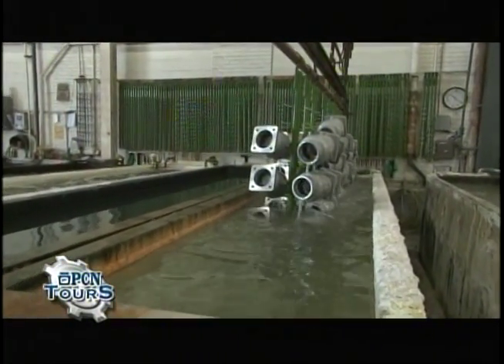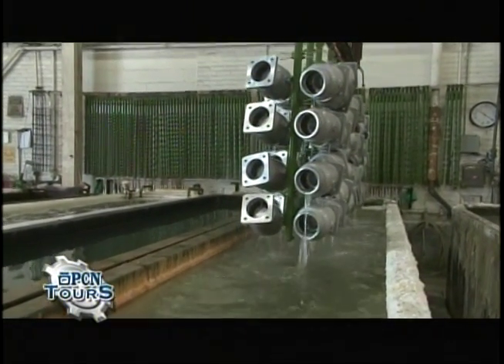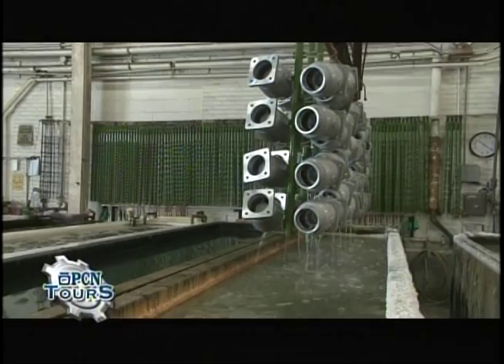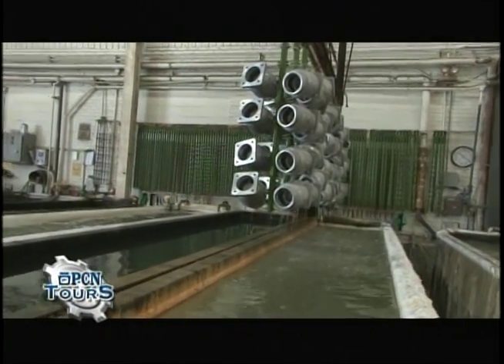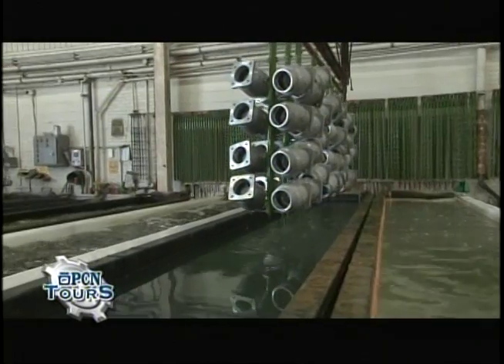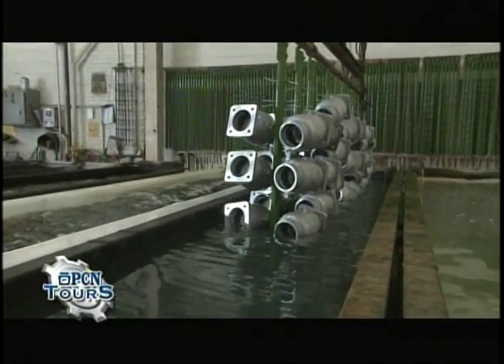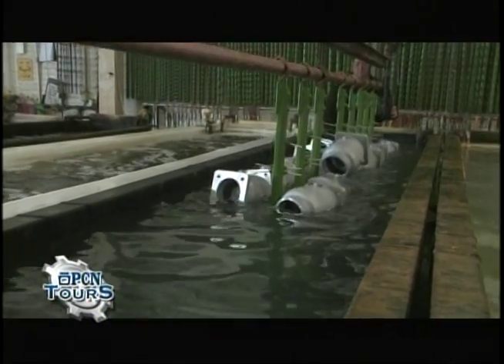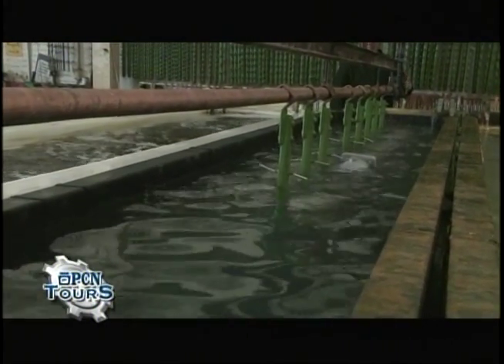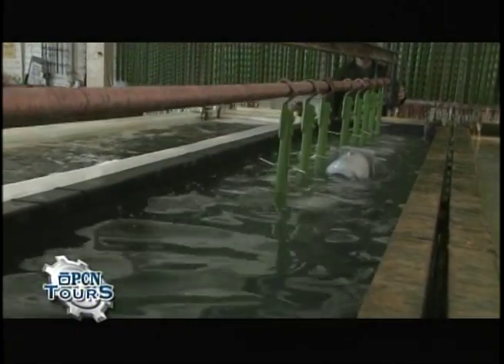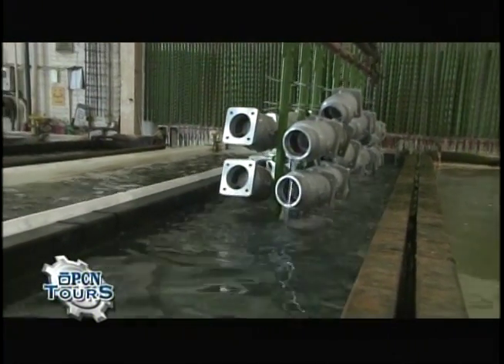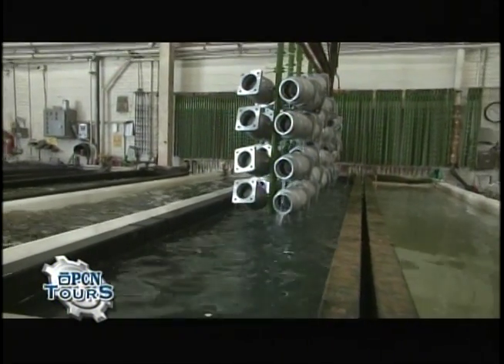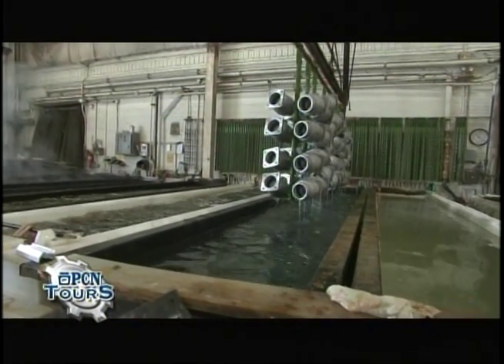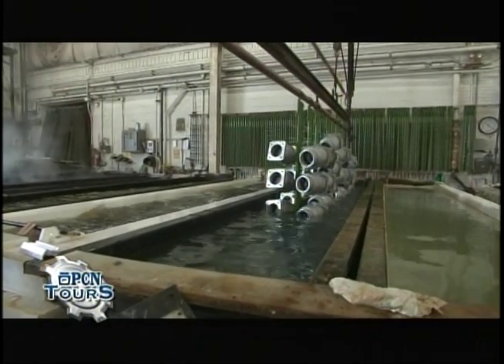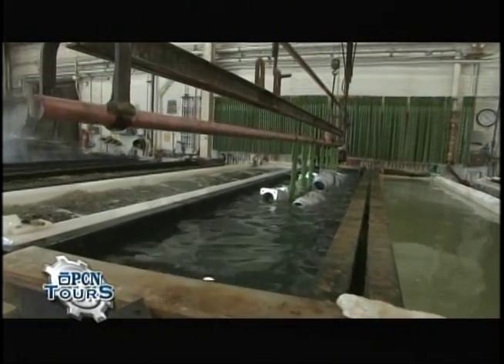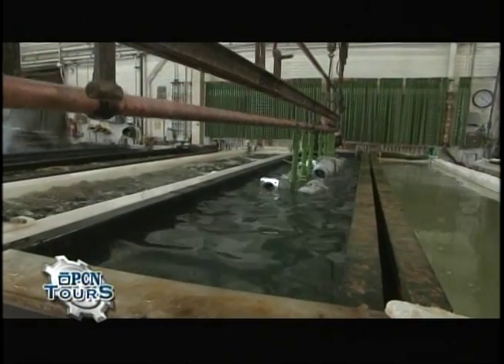It's very important that none of the cleaning solutions be transported into the processing tanks. The reason that we can guarantee such fine finishes in terms of 10,000ths of an inch is because the processing tanks are highly controlled. The amount of electricity, the temperature of the solution, the concentration of the acids, all of these variables are closely monitored and regulated. So in this case, he's making sure that these parts are completely rinsed and a perfectly clean part is put into the processing tank.